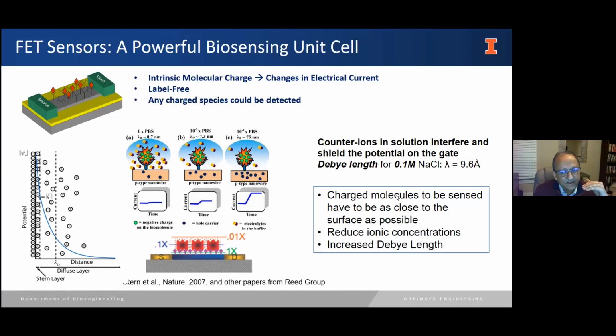If the molecule is longer than the Debye length, then it will not be able to be measured. The Debye length of a standard physiological solution is about 10 angstroms. Okay, 0.1 molar salt is 10 angstroms. So anything within 10 angstroms, you can measure. Anything more than 10 angstroms, you're not going to be able to pick up because it's neutralized.